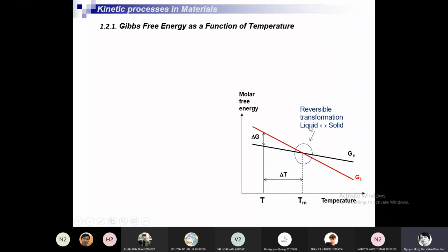So at this temperature, you have the reversible transformation, liquid to solid, and solid to liquid, because they are in equilibrium. So if some amount of solid transforms to the liquid, the same amount of liquid will transform into solid. So we have the reversible transformation. Or we can say there is no transformation here, because the solid and liquid are in equilibrium, so they can exist together at this temperature.